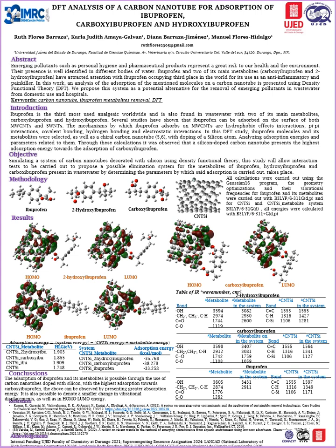For bonds corresponding to the oxygen-hydrogen group, for three molecules, that is ibuprofen, 2-hydroxyibuprofen, and carboxyibuprofen, a decrease in the wave number was noted. The 2-hydroxyibuprofen is the one that presents the greatest difference when measured before adsorption and after adsorption, while ibuprofen had the lowest displacement for the hydroxy group.